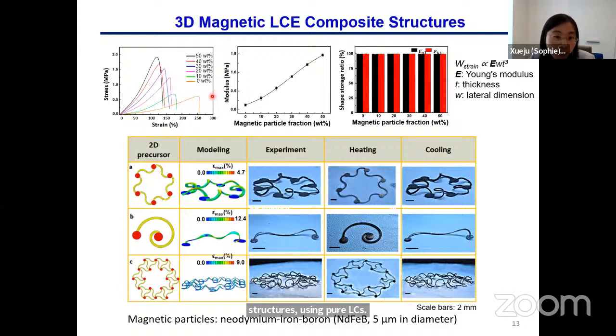Okay, so in addition to basically creating 3D LCE structures using pure LCEs, we also added other functional elements, for example, magnetic particles to the material for two purposes. First is basically to enable the very compliant structures, because as you know, the strain energy required for the compressive buckling is proportional to the Young's modulus of the material. So adding magnetic particles can enhance the mechanical properties of LCE structures. The second purpose is to enable magnetic actuation, which is fast and remote beyond the thermal actuation.